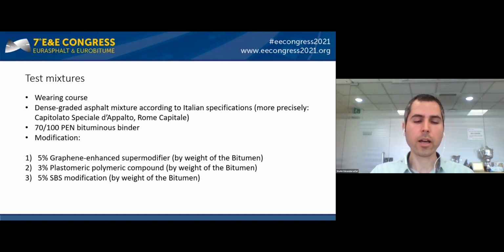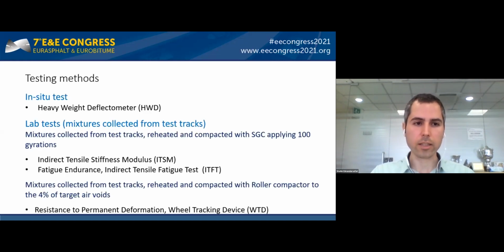The mixture was a dense graded asphalt mixture, and the bitumen was a 70/100 bituminous binder. And the dosages, as you can see here, were 5% for the graphene enhanced super modifier, 3% for the plastomeric polymeric compound, and 5% for the SBS modified mixture.